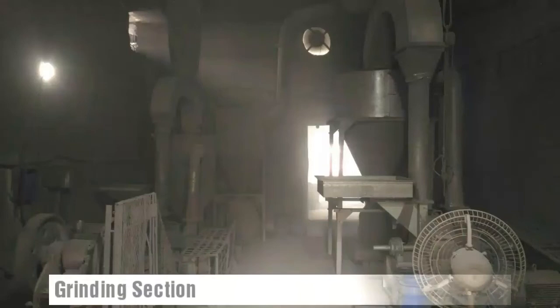In this section, large pieces of alloy are fed to a jaw crusher, then further grinding is done in a pulverizer to get a particle size of around 200 mesh. The pulverizer is also attached with a cyclone separator to discard unwanted particles.